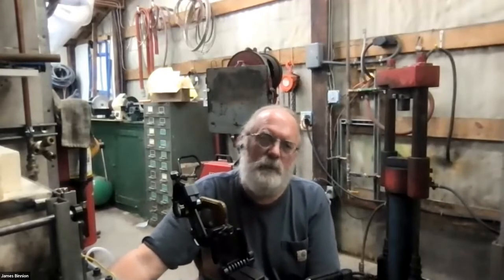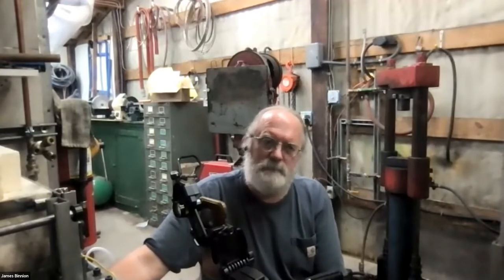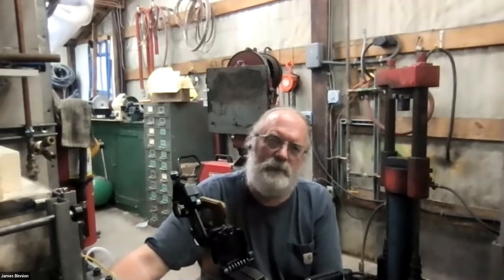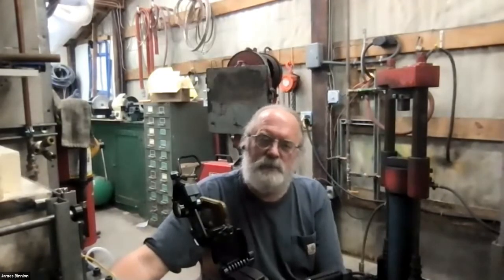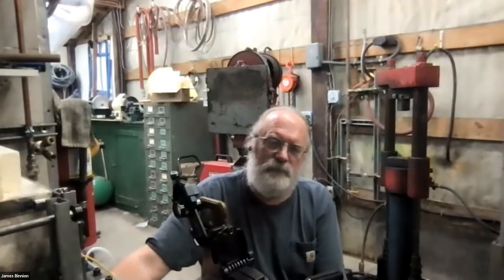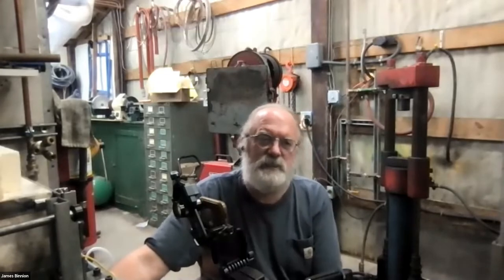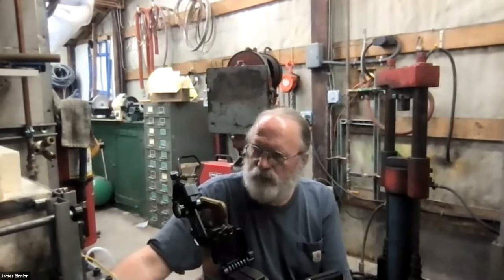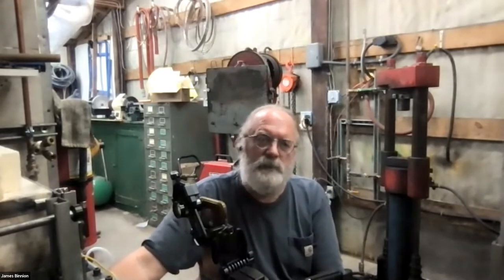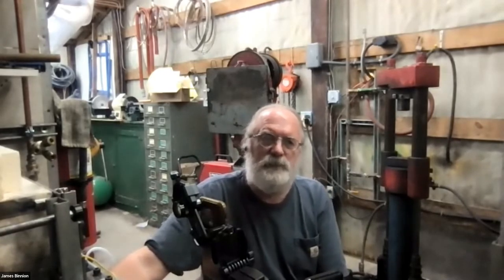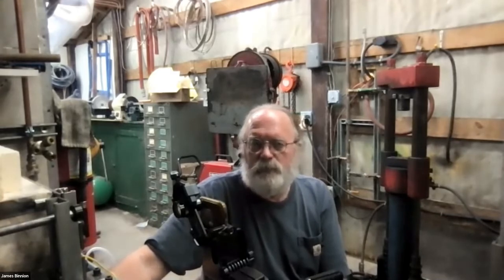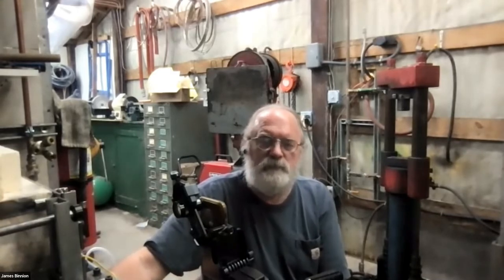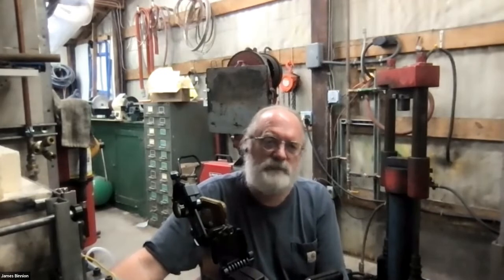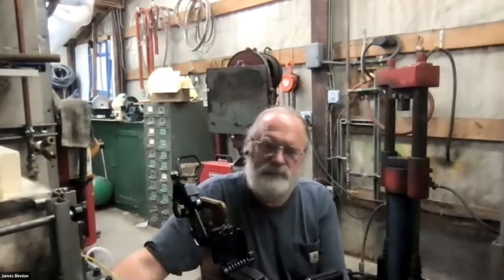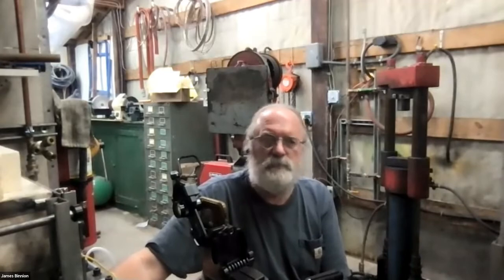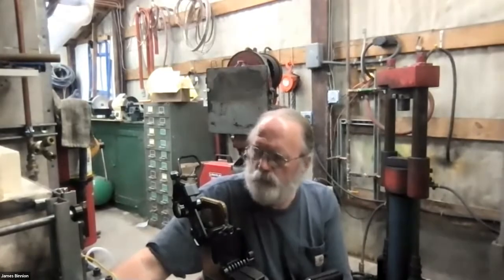You can also avoid the problem if you have a passivated or a self-passivating metal, like if you can say bond stainless steel to silver, you won't have a corrosion problem, even though normally the steel would have an issue with the silver. The chrome oxide that forms creates a passive layer that prevents the material from being corroded.